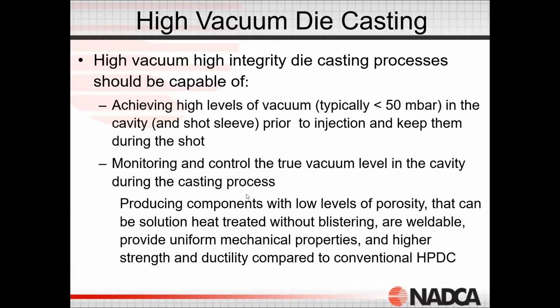So when we produce a casting from a high vacuum process, and we produce a structural casting, these castings have extremely low levels of porosity. These castings can be solution heat treated without blistering. They're weldable. They have good uniform mechanical properties. They have higher strength as compared to standard high pressure die casting. So we get some good mechanical properties, and ultimately they have better elongation.